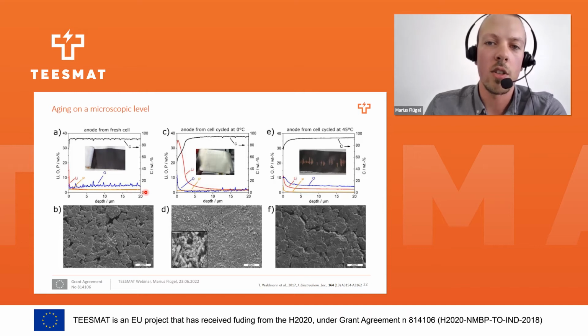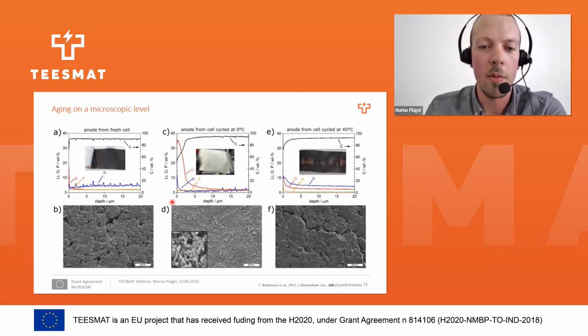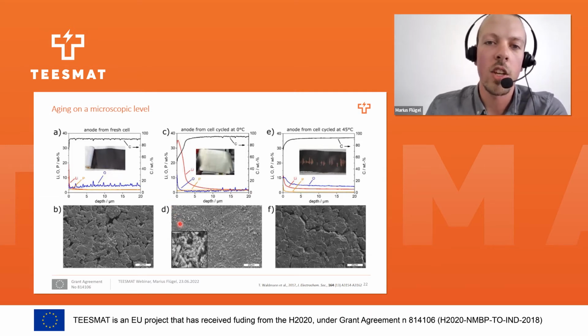After aging at low temperature, which leads to lithium deposition on top of the anode, we see a film which covers completely the surface, and we cannot see the graphite particles any longer. At higher magnification, we can see the dendritic lithium, and with GD-OES depth profiling, we found that the lithium deposition was only happening on top of the anode.